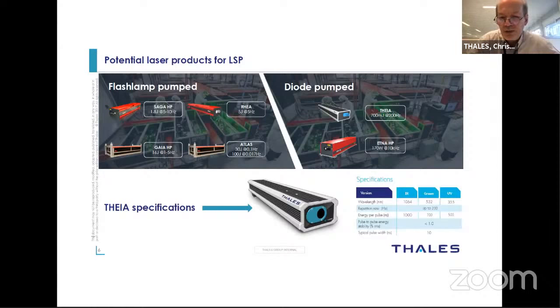And the other interesting thing, so the first lesson is that you are performing a better quality laser shock peening. The other interesting thing is this new generation of laser has a much larger average power, and the average power will determine the speed of the process. So it means the speed of the peening process will also increase. So we find these solutions will be very effective for laser peening, and that's also a lesson.